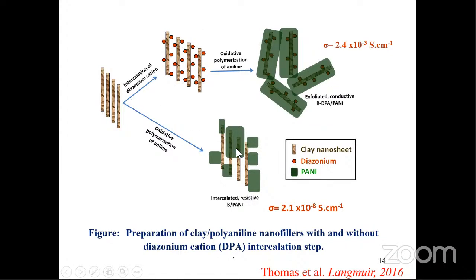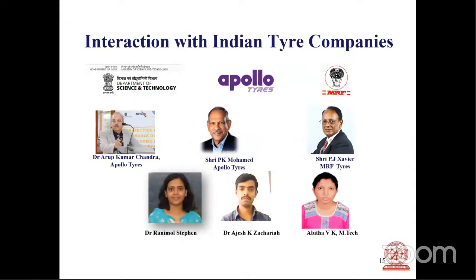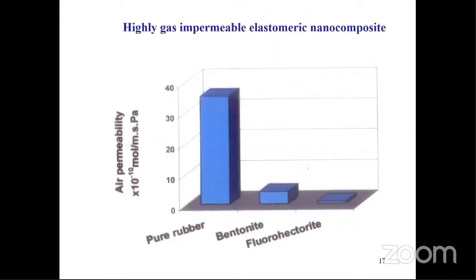Another one without surfactants. When we polymerized the aniline on the surface of clay without surfactant, you know what we got? We got an interconnected system, the mechanics were very poor, and conductivity was lower. But when we did a surfactant modification, then polymerization of aniline, we got a fantastic, excellent nanocomposite. We applied this in tire engineering. I'll show you a couple of slides.